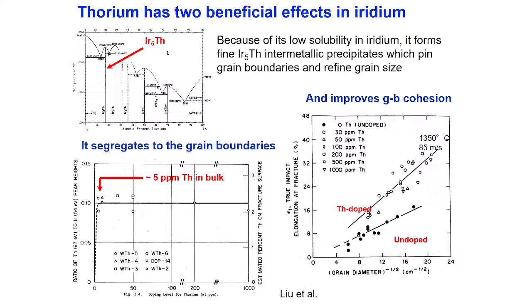To study the grain refinement effect, you go down this axis, pick any one grain size and go up, and you find that for a fixed grain size, the undoped material is always more brittle than the doped material. Or the other way to look at it is, if I pick any one thorium concentration and change the grain size, this is inverse square root of grain size, so grain size is decreasing here and decreasing there. This move along this line is a grain size effect, and the difference between this curve and this curve is the grain boundary segregation effect.